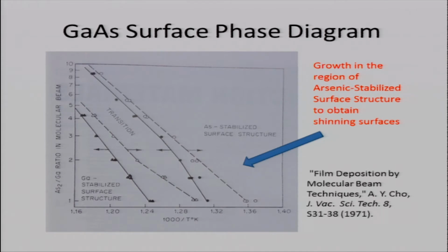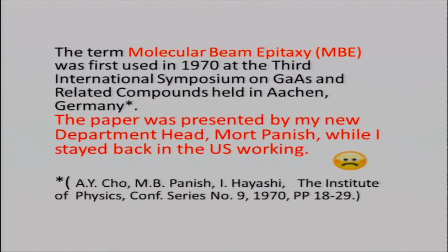As you all know, today, when we grow a shiny, smooth surface, we always want to grow an arsenic stabilized surface structure. Why? It's just like John Arthur earlier showed, any additional arsenic atoms just bounce off anyway. It doesn't matter. So as long as you have enough arsenic atoms on the surface, you grow a shiny gallium arsenide surface. But too much gallium on the surface, what happens? You get gallium beads on the surface. You get a hazy surface, finished. Okay? So therefore, we always grow on the arsenic stabilized surface structure.